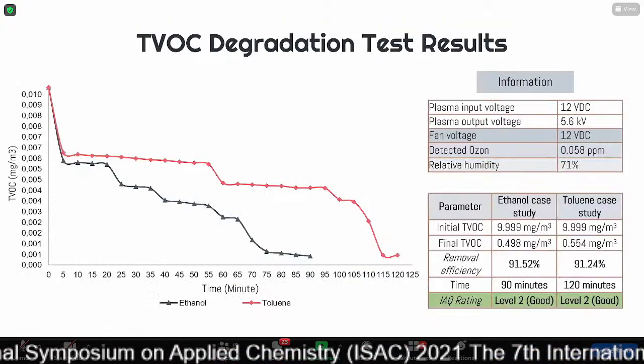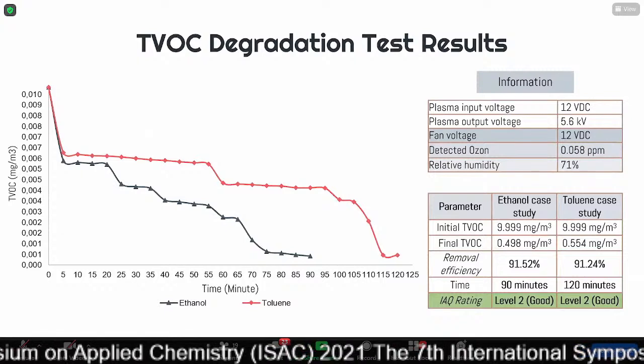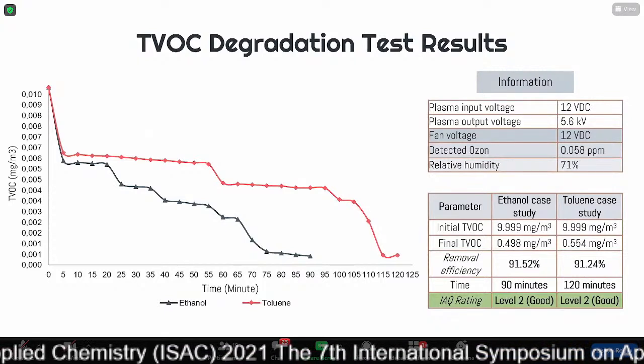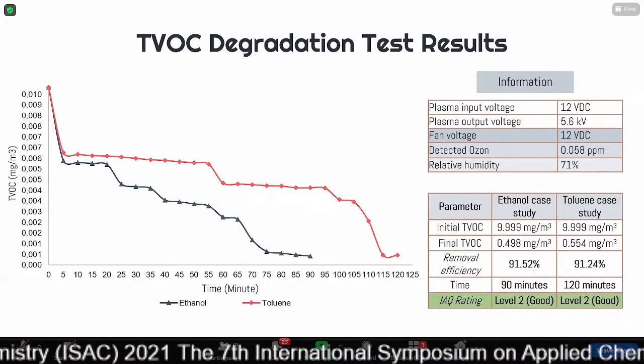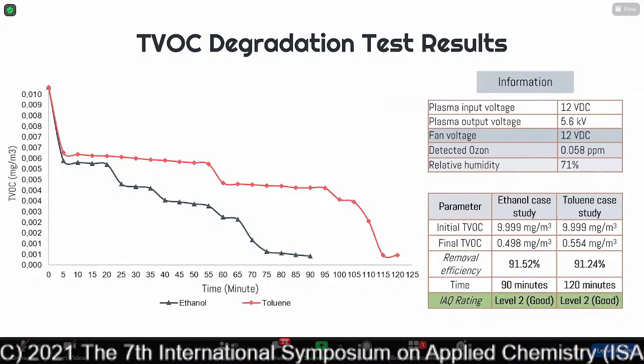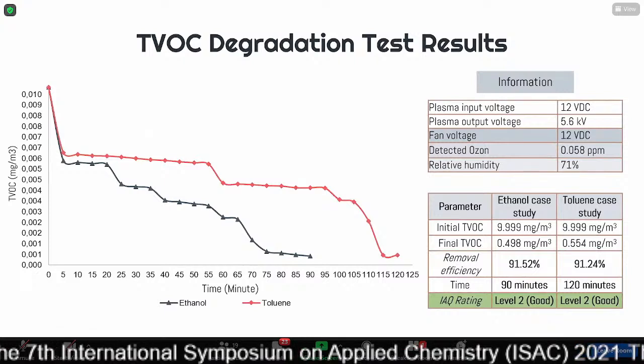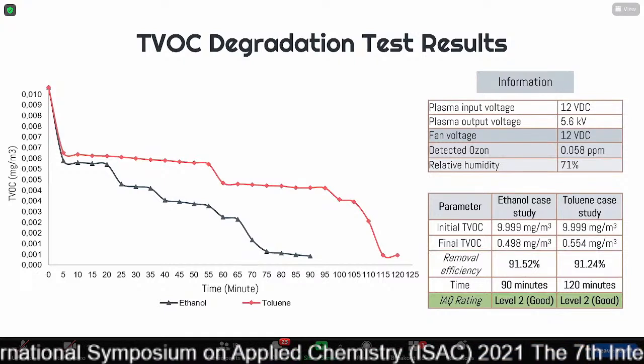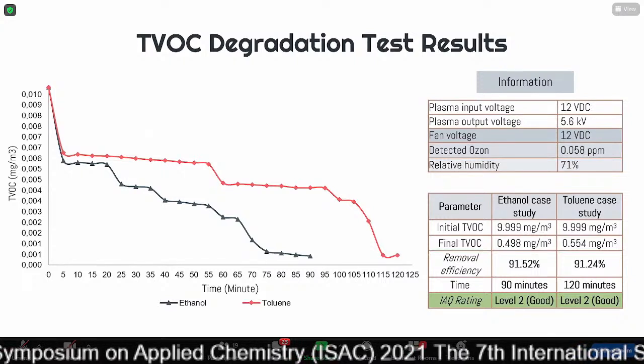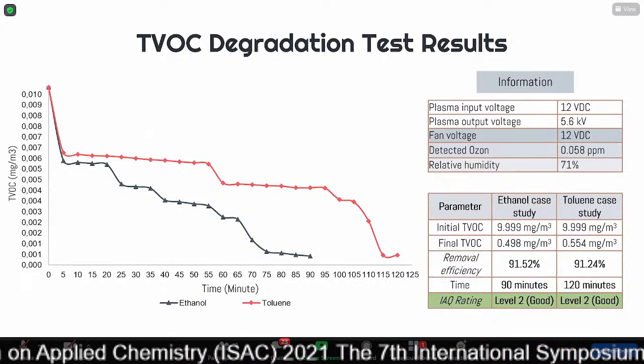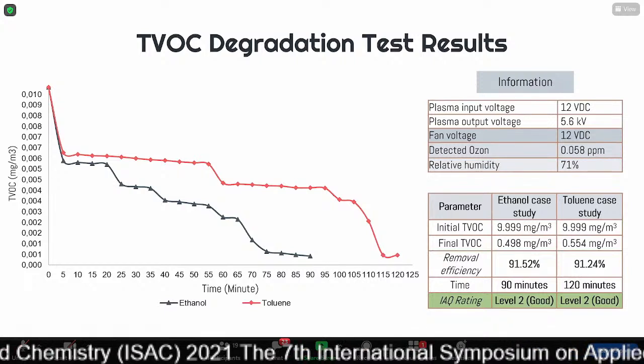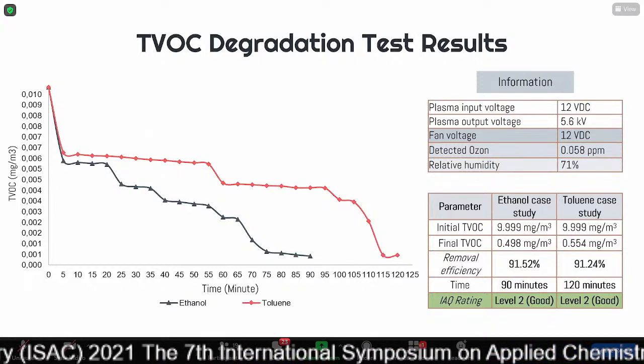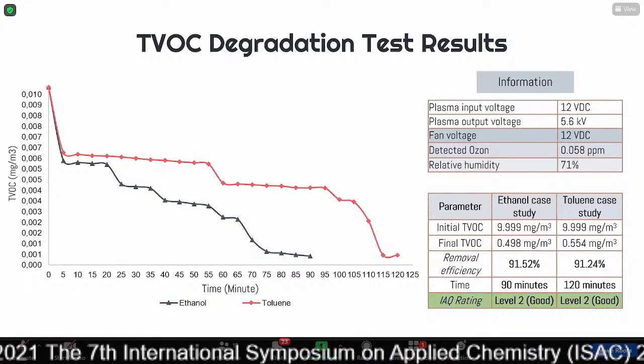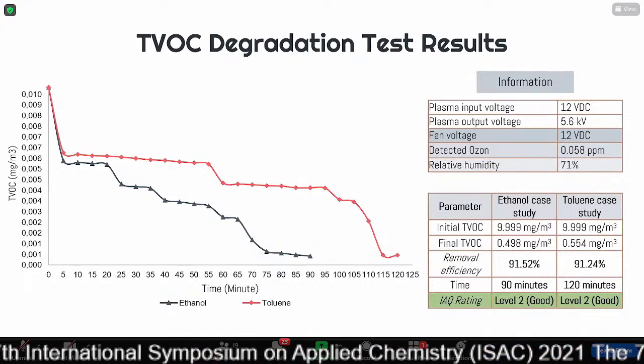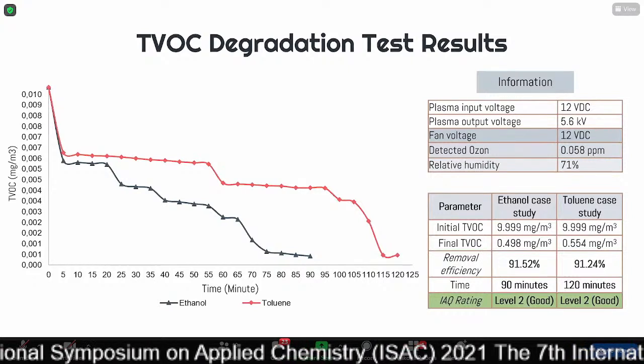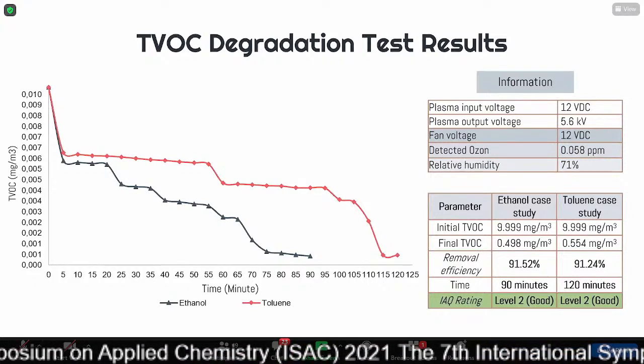And this is the TVOC degradation test result. Based on the graph on the following slide, it can be seen that total VOC concentration in the ethanol case study decreased by 91.52% over 90 minutes, with the final TVOC concentration of 0.49 milligram per cubic meter. Meanwhile, in the toluene case study, the TVOC concentration decreased by 91.24% over 120 minutes, with the final TVOC concentration of 0.55 milligram per cubic meter.